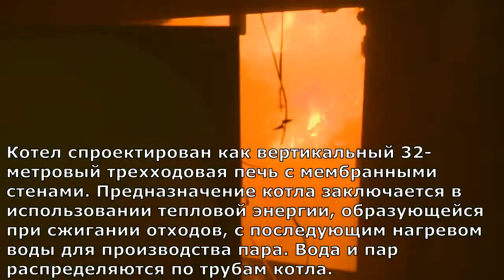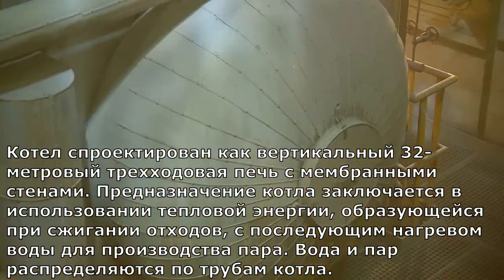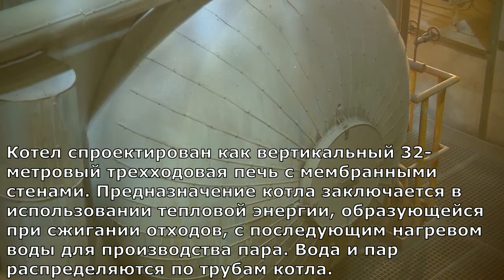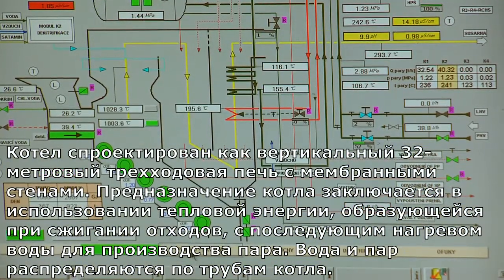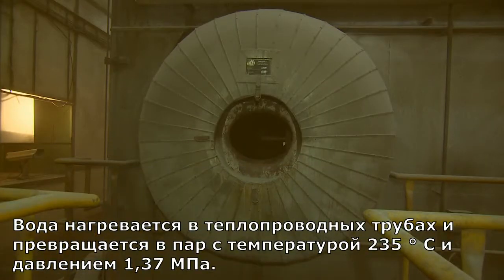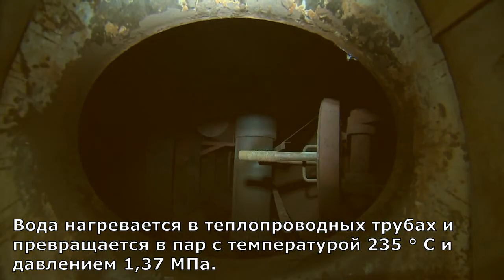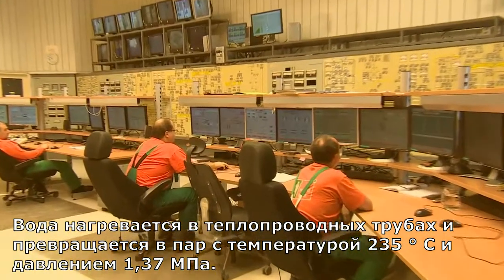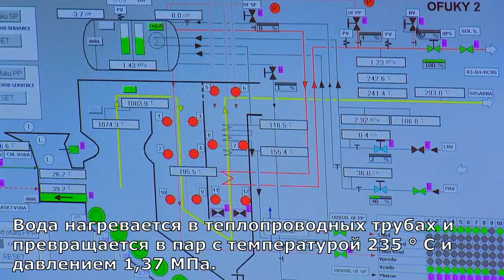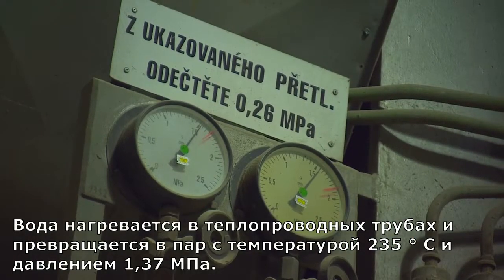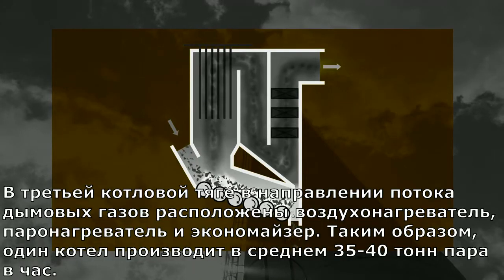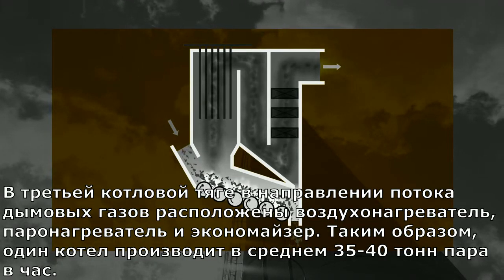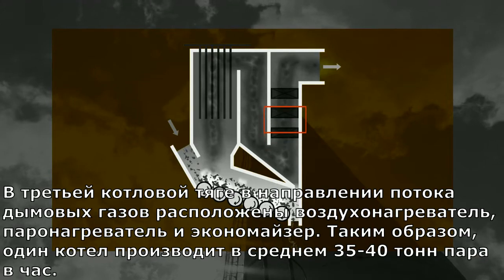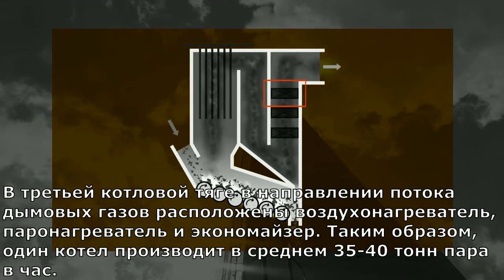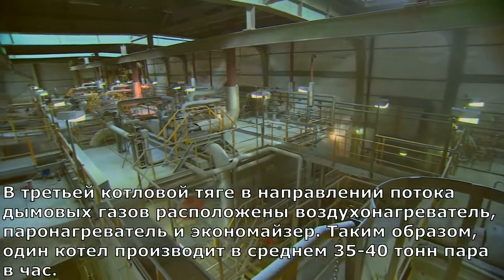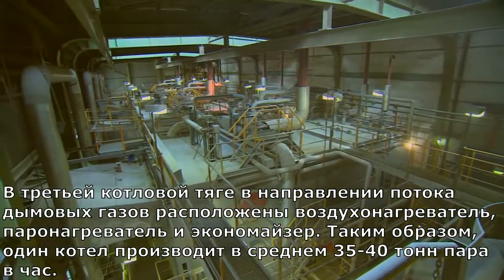The boiler is designed as a vertical 32-meter high boiler with 3 drafts and membrane walls. The purpose of the boiler is to use the thermal energy produced by burning the waste to heat water to produce steam. Water and steam are distributed by boiler tubes. Through the heat exchange surfaces of the tubes, water is heated and turns into steam, with parameters of a temperature of 235 degrees Celsius and a pressure of 1.37 MPa. In the third boiler draft, an air heater, steam superheater and economizer are situated in the direction of the flue gas flow. One boiler thus produces on average 35 to 40 tons of steam per hour.